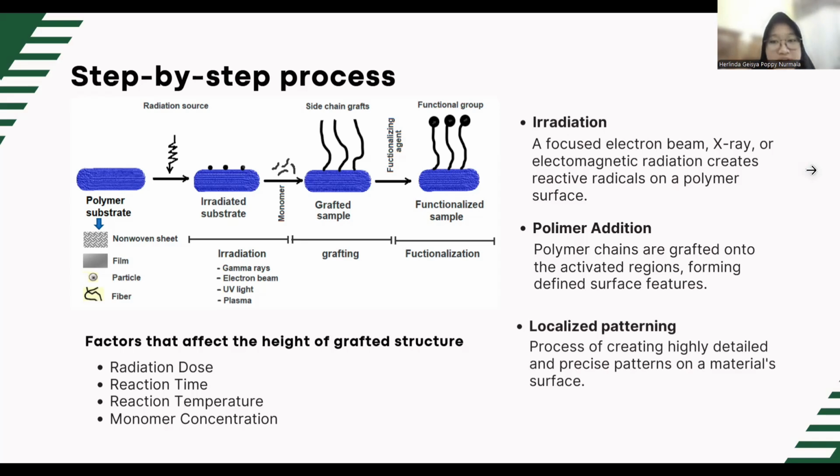Also, there are several factors that affect the grafted structure. The first are radiation dose, reaction time, reaction temperature, and monomer concentration, where enhancing all of these factors would lead to a taller and greater structure. Move to the next slide.